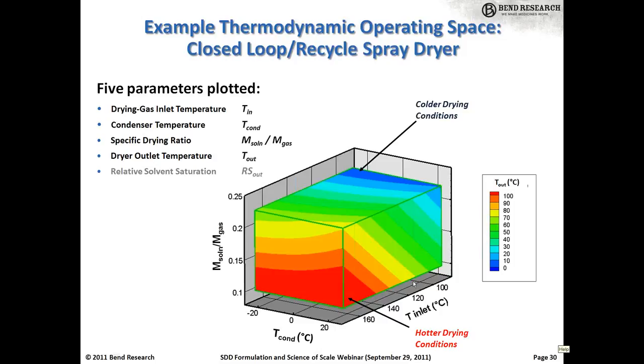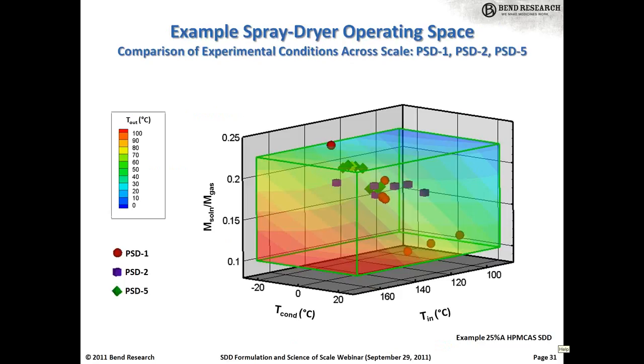So we're showing, again, the inlet temperature of the spray dryer, the condenser temperature, again, the solution feed rate and gas feed rate, and contours of constant outlet temperature within the cube here. So the hotter drying conditions are up front and the colder are near the back. So on this next slide, we're showing an example of a 25% HPMCAS SDD experimental conditions where we've plotted PSD1, PSD2, and PSD5 spray drying conditions.